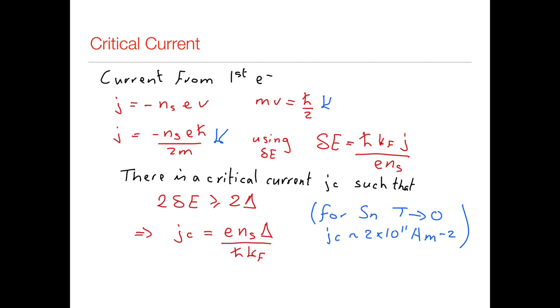Well, the amount of current I can pass before driving the material normal is now lower, because there is already a current that's coming from the screening. So there's the screening current, and it's the sum of that screening current plus the actual current that I'm passing through the material. And it's when that sum is equal to Jc that we drive the material normal.